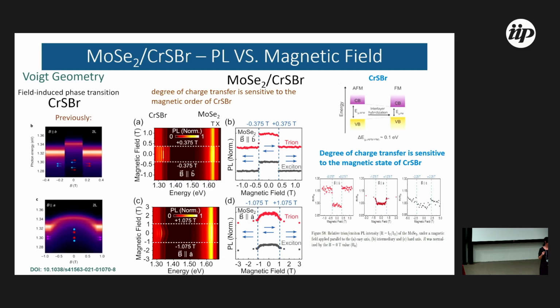If the band gap of CrSBr is changed, you change the band alignment. If you change the band alignment, the amount of charge transfer is changed, and the doping is changing. So it's a very nice system: the phase transition modifies the charge transfer, and you can probe this.